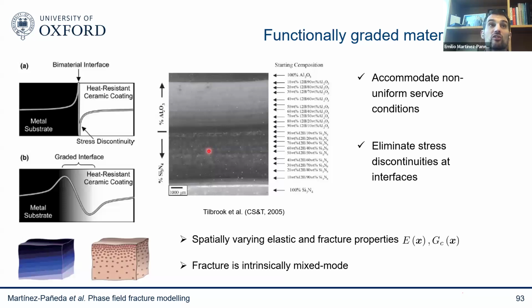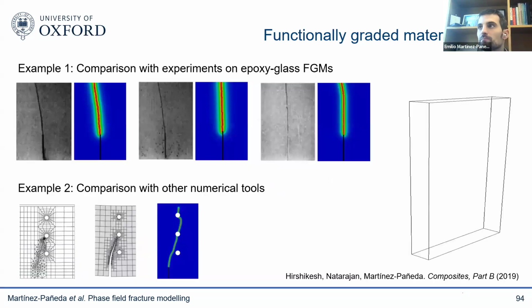And they're very interesting from a fracture perspective because their elastic and fracture properties vary in space. And this means that your fracture is going to be intrinsically mixed mode. Your stress intensity factors are not going to be only K1. Even under conditions where you have purely mode 1 fracture, so a crack in a uniaxial tension sample, you're going to have crack deflection and mixed mode conditions just because the crack is seeing a material gradient in front of it.